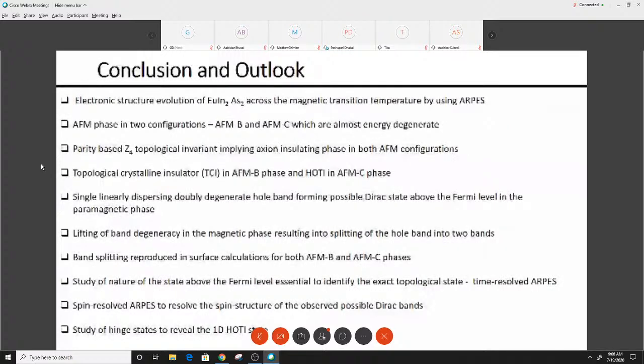We also calculated the approximate position of the Dirac point in the paramagnetic phase. However, time-resolved measurements are necessary to accurately resolve whether there is actually a Dirac point or there is a small gap in the states. So in the future, we wish to study time-resolved ARPES and spin-resolved ARPES to resolve the spin structure of the observed Dirac bands, and also the hinge state to reveal the 1D HOTI state.